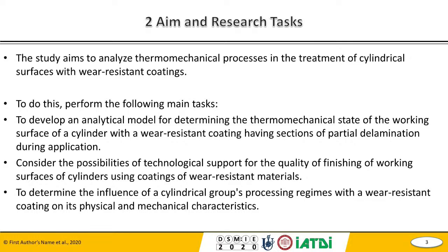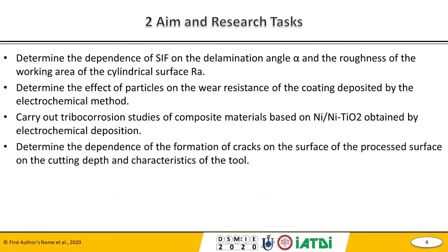Slide 4, please. Determine the dependence of the stress intensity factor on the delamination angle alpha and the working area of the cylindrical surface. Determine the effect of particles on the wear resistance of the coating deposited by the electrochemical method. Carry out tribocorrosion studies of composite materials based on nickel and titanium dioxide obtained by electrochemical deposition. And the last one is to determine the dependence of the formation of cracks on the surface of the processed surface on the cutting depth and characteristics of the tool.